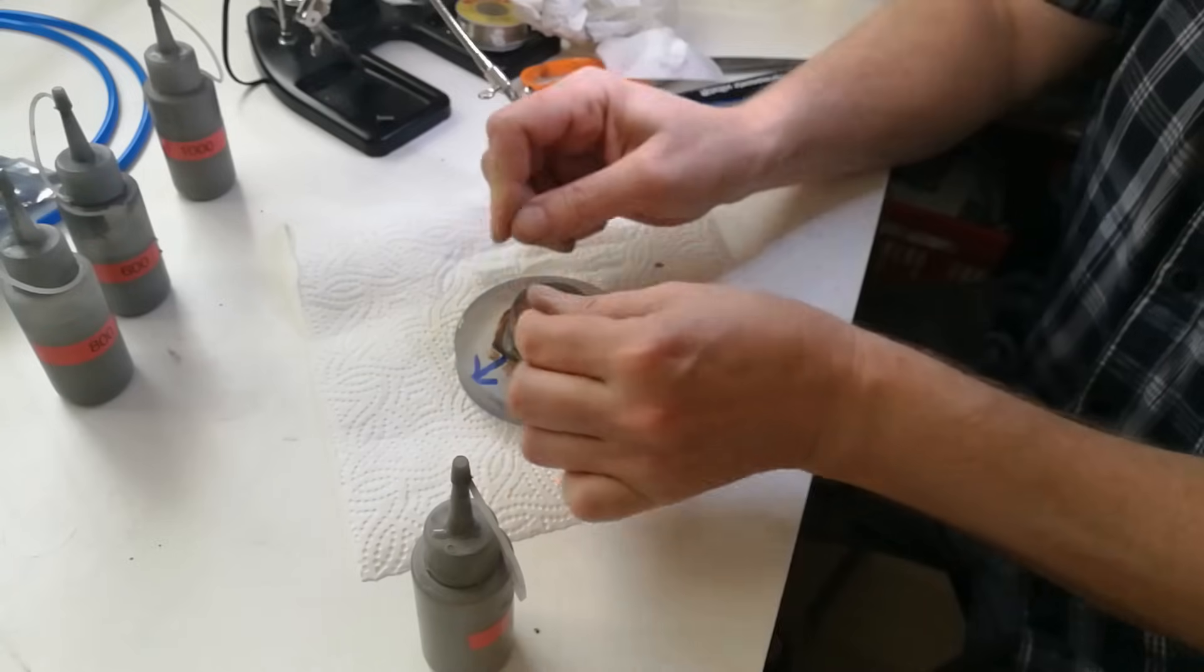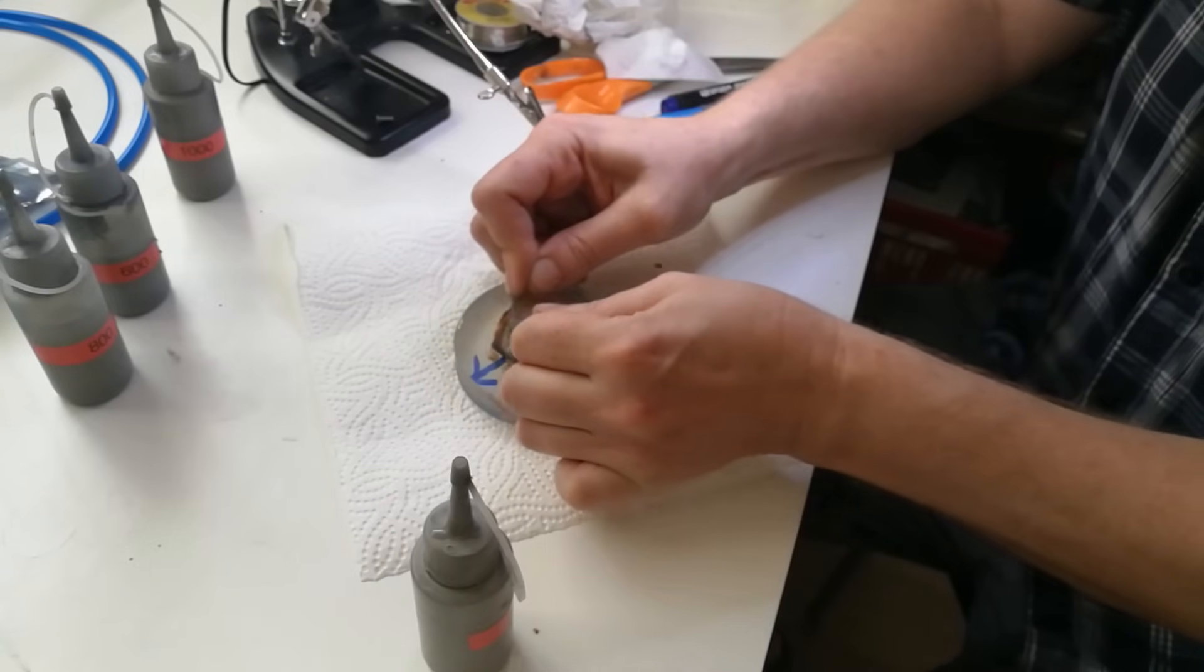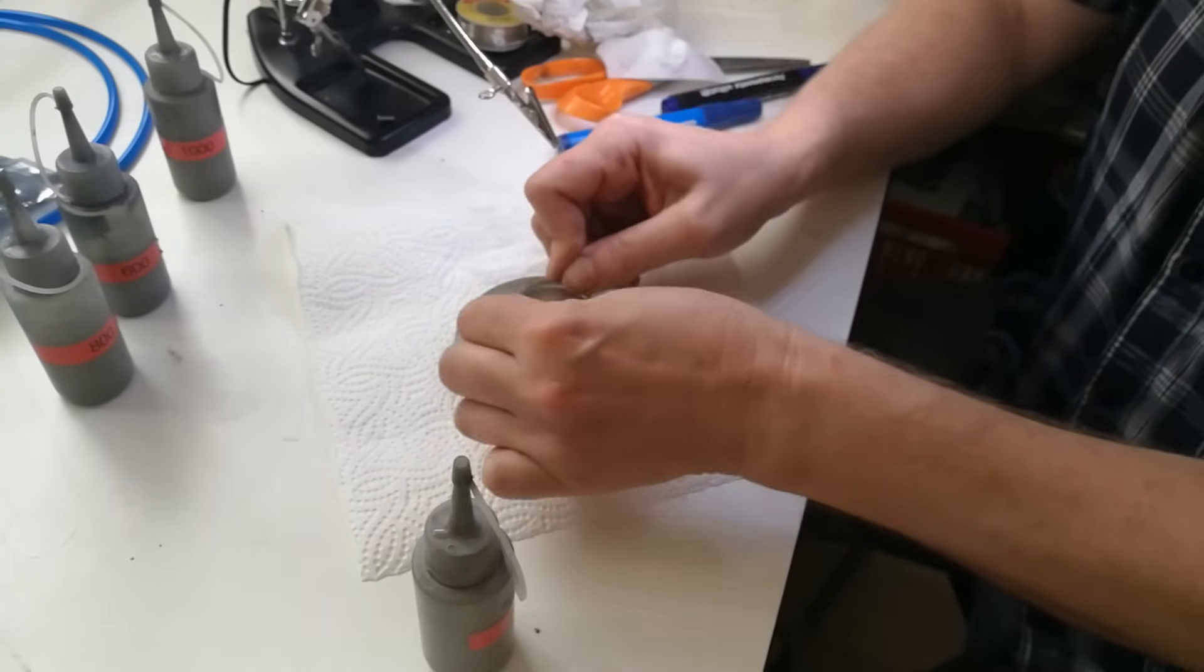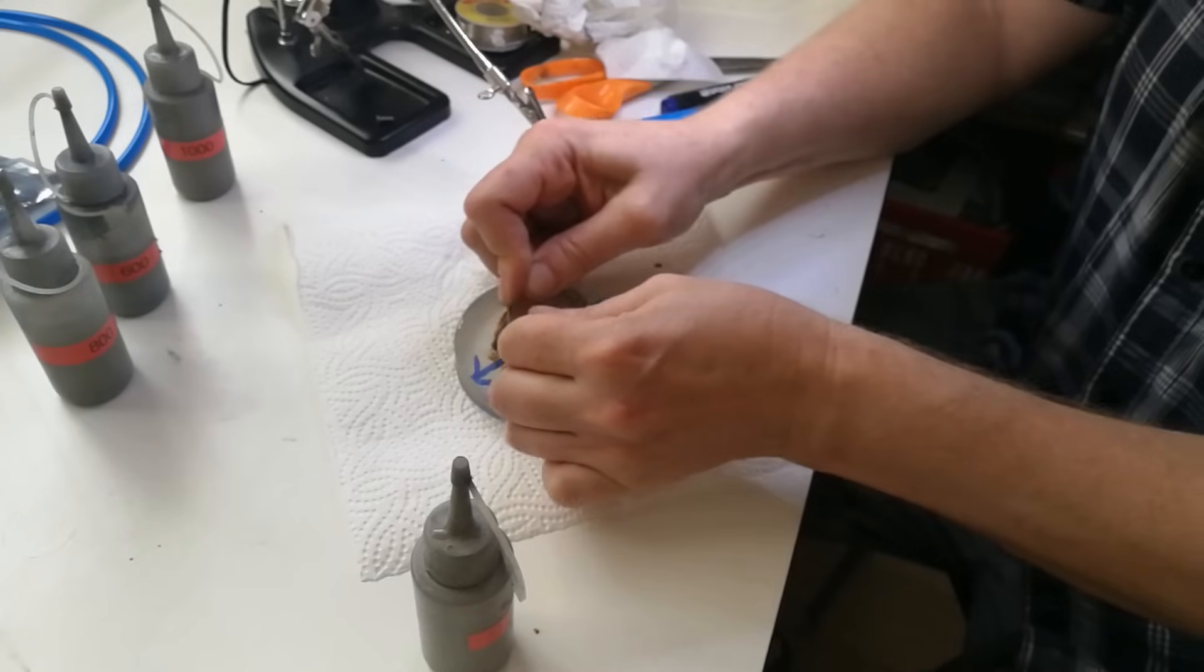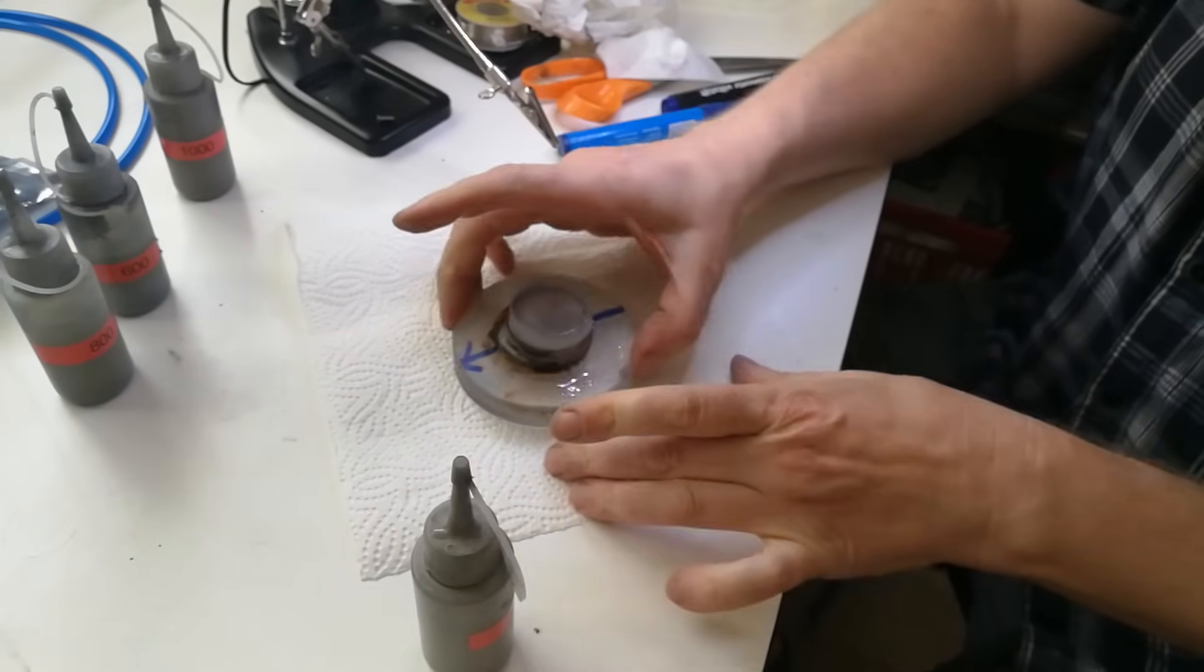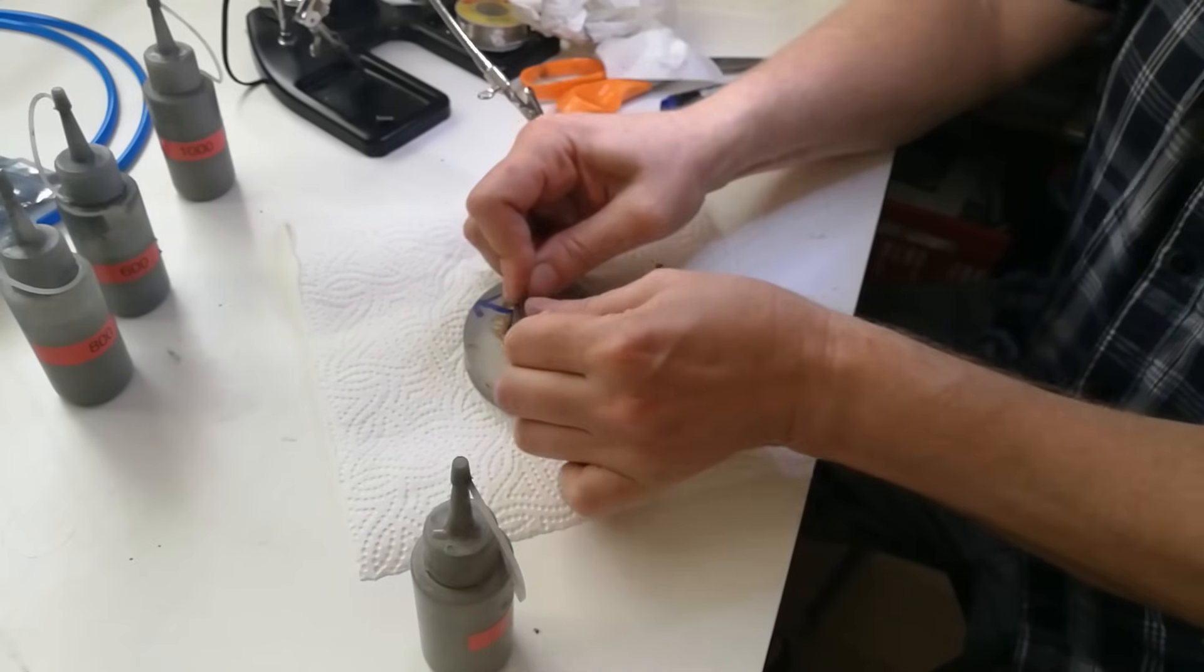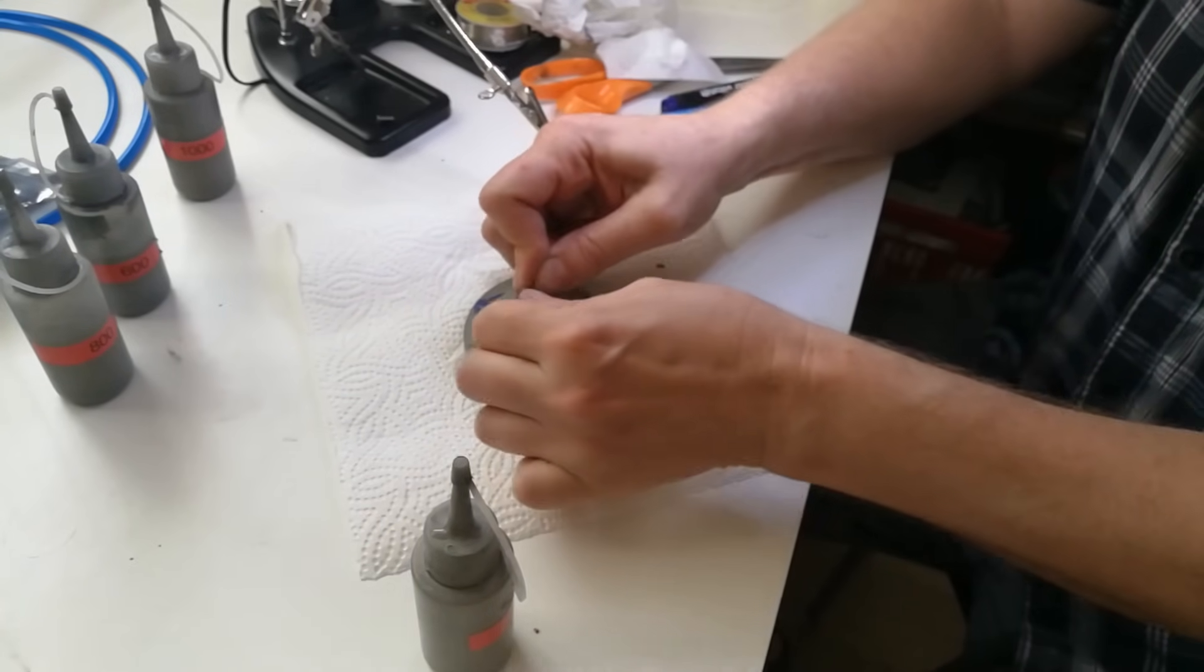If you observe roughness variations between for example the center and the edges of the blank, the grinding strokes are probably too long. This leads to aspherical surfaces, and aspherical surfaces cannot make good contact with each other.